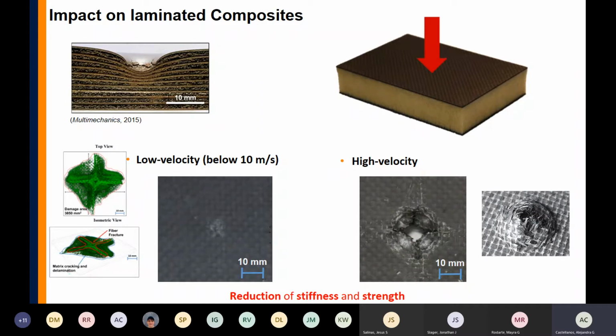If you see a high velocity impact, you will see there is damage, so we either have to replace it or repair it. But in a low velocity impact, you don't know exactly what is going on inside. That's one of the things that my research group studies. In the case of low velocity impact, there will be a reduction of stiffness and strength after foreign objects impact the laminated composite.